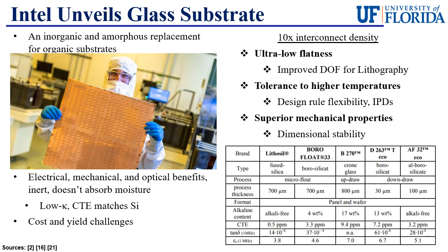In pursuit of an even better packaging substrate solution, major semiconductor players like Intel have been researching and developing the glass substrate for over a decade as an inorganic and amorphous replacement for the popular organic substrate. The glass substrate possesses extremely desirable electrical and optical properties, is chemically inert, and is highly resistant to moisture. Its low dielectric constant makes it easier to isolate conductive interconnects, but greatly improves signal integrity, and the coefficient of thermal expansion is perfectly matched to silicon. That's because most glasses are silicon-based, with other additives hidden behind proprietary brand names such as Lithosil or Borofloat.